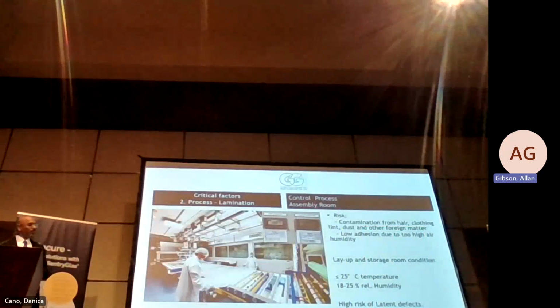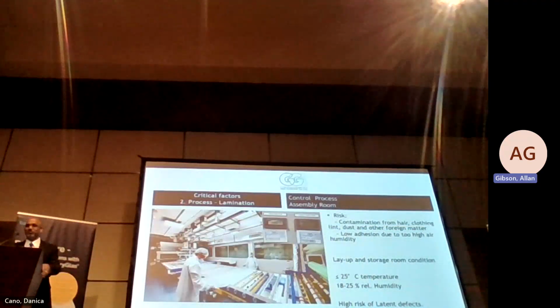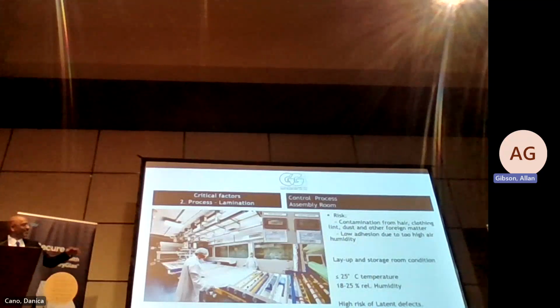Room conditions. You look at this guy, they enjoy working here for the next 3 months because the temperature inside there is less than 25 degrees. Relative humidity is 18 to 25%. So that sort of control condition is very critical because once you supply the laminate to your project, it looks perfect. The problem starts after 3 years, 4 years, 5 years.